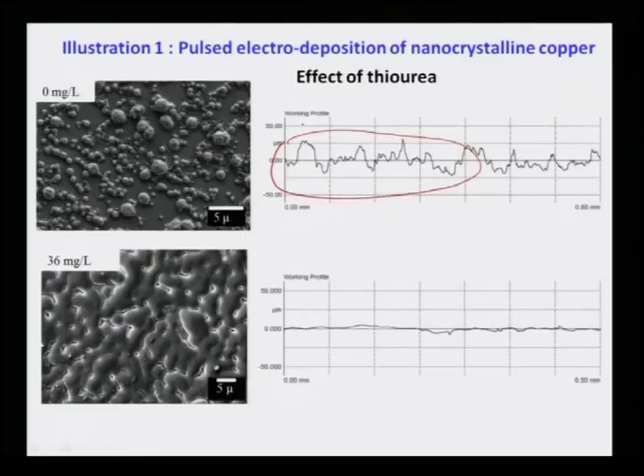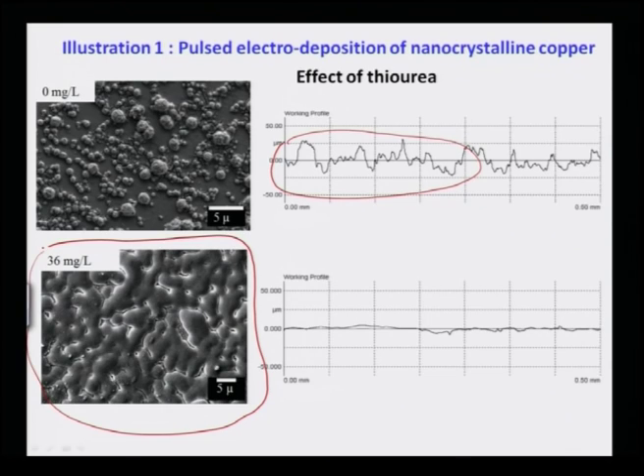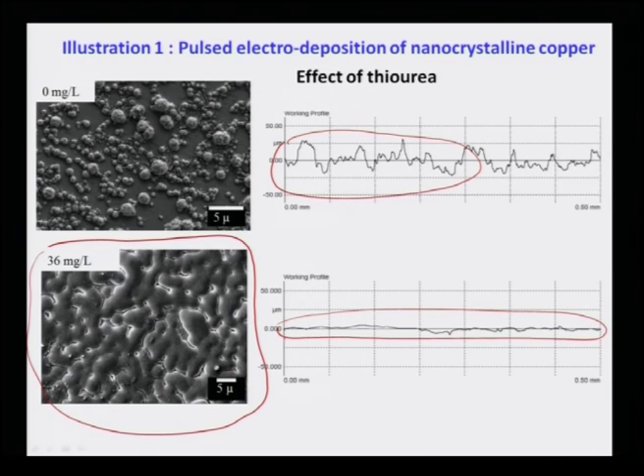If you add 36 mg/L of thiourea, the surface roughness becomes very very low — roughness can be easily controlled by thiourea addition. This is exactly what is required when copper is deposited on PCB boards or vias in electronic circuitry. This was observed nicely using scanning electron microscopy followed by laser surface profilometry — two advanced characterization techniques.